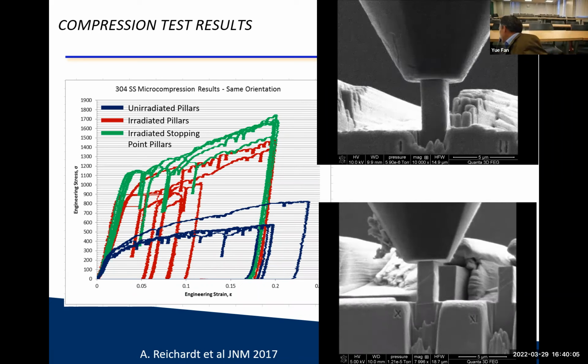So all the deformation actually only happens at these two locations in this instance. The rest of the pillar doesn't deform much. And we can relate these events to load drops in the stress strain curve. What happens is all the deformation happens at very localized regions. And when this happens, you see the load drops because it's under stress. And when the deformation goes, it overreacts, like when somebody pushes and you push back, and then you do this opposite motion. It's a slight failure in the feedback loop. That's why you have this load drop.